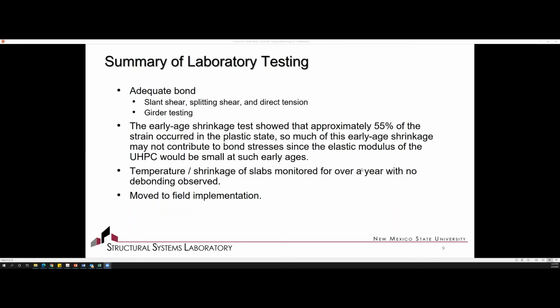So based off of all of this, the laboratory testing, we identified that we had adequate bond strength. We saw that with all of our different testing that we did on both the small specimens as well as the girder test. With the early age shrinkage test, we showed that the majority of that occurred in the plastic state. So we didn't really expect this to contribute to the bond stress too significantly at the early ages, as it was pretty young concrete.